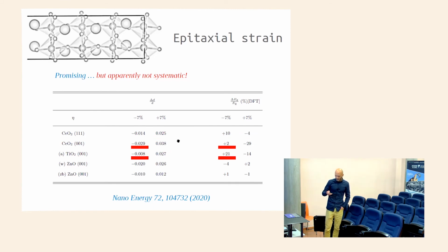And in the same way, here we compare two different materials. We have a very large expansion of the bonds of relevance here, and a very small one there. However, if we look at the response of the materials, despite this small change, because the system is quite stiff from a mechanical point of view, the change in the energy bandgap is huge, whereas here we have a huge structural change, and the change in the energy bandgap is just small, right?